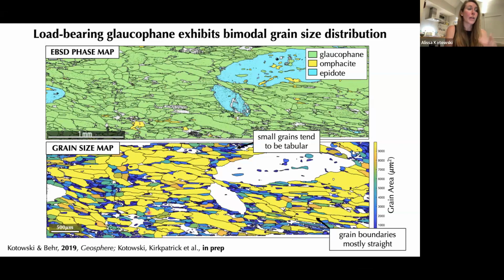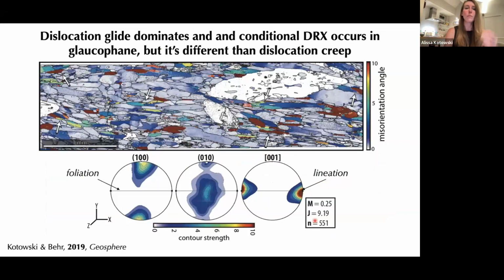This is comparable again to the hornblende sample, where we have large yellow grains surrounded by small blue grains. But now these small grains tend to be more tabular in shape, whereas the other ones were more equant or polygonal. Our grain boundaries here are also extremely straight, which is different from the hornblende microstructure. If we look at the misorientation map, then we also see very systematic movement of dislocations through these grains. So we're also seeing very specific slip planes and directions that are accommodating this dislocation movement.